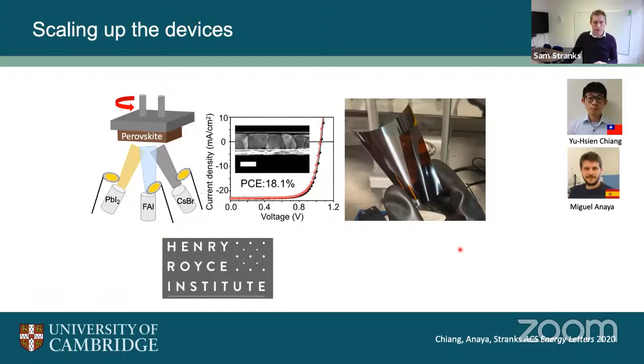And then one of the other topics I wanted to talk about briefly was scaling up the devices. How can we move them from small area in the lab up to much larger area? Some work we're doing is not just using solution to process them, so using inks, but actually using vapor methods where we have the precursor salts and we sublime them onto the substrate. This is called thermal evaporation. So we heat them gently, and then these materials form very uniform layers on the substrate.